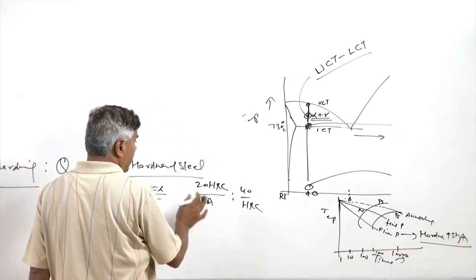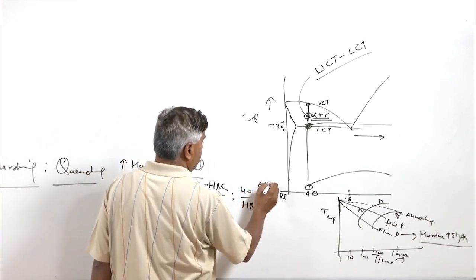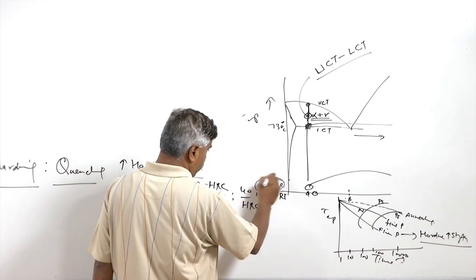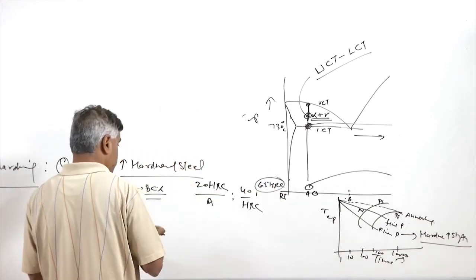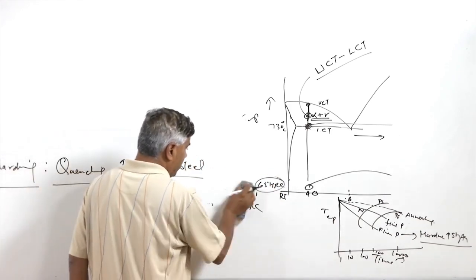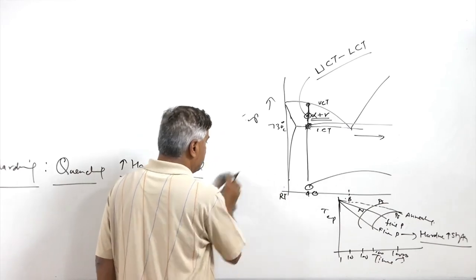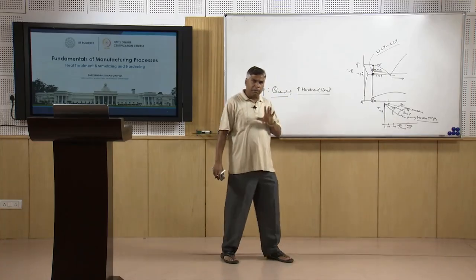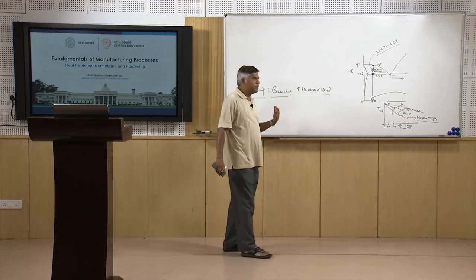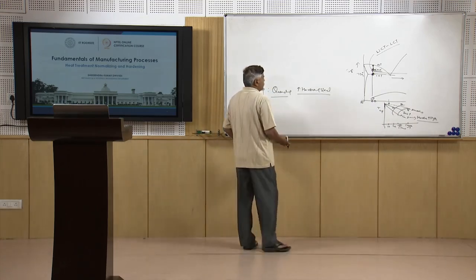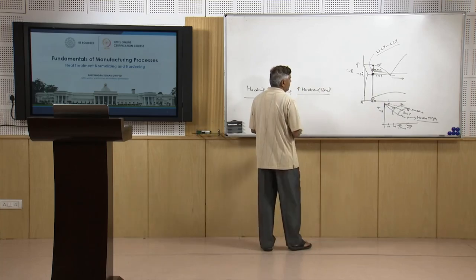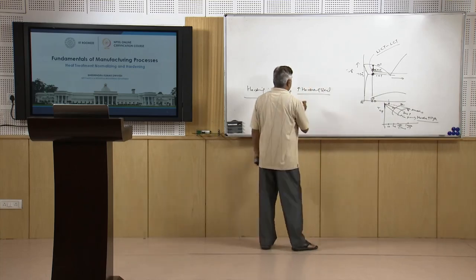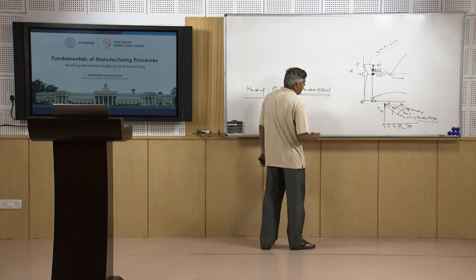But after the hardening we may get as high as 65 HRC. So a significant increase in the hardness is realized when hardening is carried out for the same composition of the steel. Steel offers such kind of capabilities wherein the properties can be altered over a wider range by changing the structure.